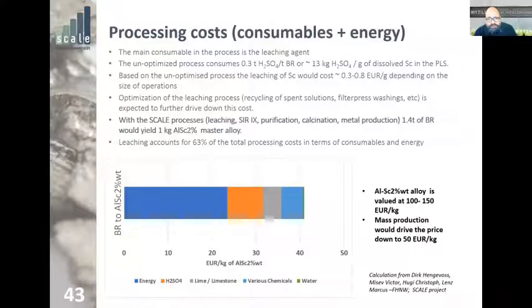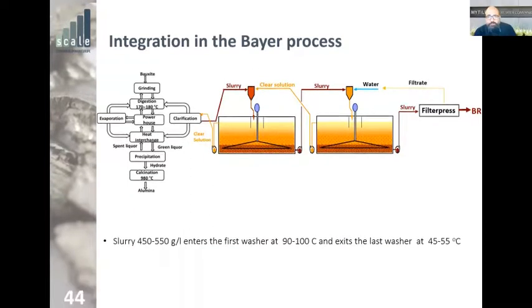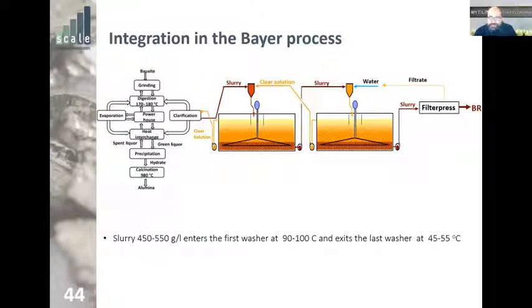Still, we estimate, even with these very draft calculations, about 40 euros per kilogram for the aluminium scandium alloy, only on operational costs, excluding personnel. And as I said before, the price for this is 100 to 150 euros per kilogram. But you should expect that once you start a mass production of this alloy and there's a mass demand, the prices could be as low as 50. So there is room, not huge room to celebrate, but there is still a viable window there. And what's more important is to understand that there's a significant cost reduction to be had when this process is integrated in the Bayer process.